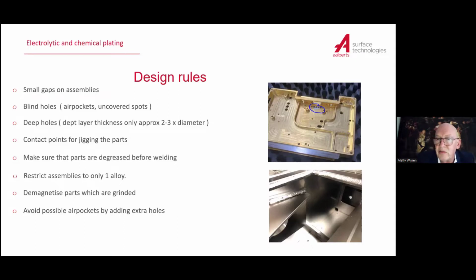And this is one of our bigger parts, which we chemical nickel plate. And you see, this is the inside of the part, which has to be plated, but which also has a lot of possible trapped air pockets, which have to be dissolved by the wetting technique. If we were in contact with the designer of this part in advance, there would be no problems. Now every time it's: is this okay? Yes or no? We have to be pleased. So that's something which is taken.